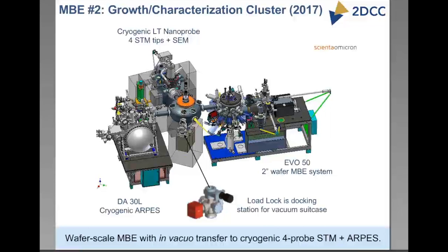This has an SEM in it, and it allows you to guide 4 STM tips onto a sample surface, and you can do 4 probe measurements as well as spectroscopy currently with 1 tip, but in the future you can do the scanning with all 4 tips. That's when we put that into place.